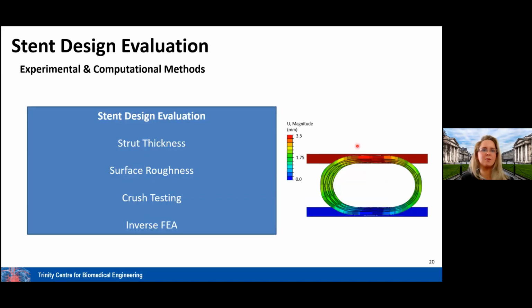So let's evaluate these a little bit then. Have they worked? Do we get reduced strut thickness? How does that affect our surface roughness? Can we carry out, for example, crush testing to look at the performance, the radial stiffness of the stents, and are they suitable for going into a coarctation and opening up those vessels? And then the final thing I'm going to show you is this inverse FE that we do in order to ascertain the actual mechanical properties of the titanium when we print it, because we cannot assume it's the same as the bulk properties of titanium. 3D printed titanium or any metal when printed can be very different from a bulk as-cast material.